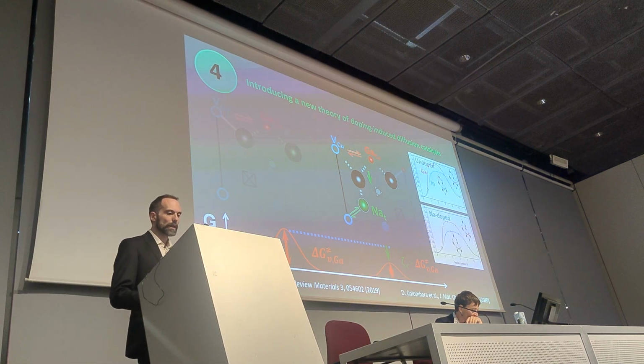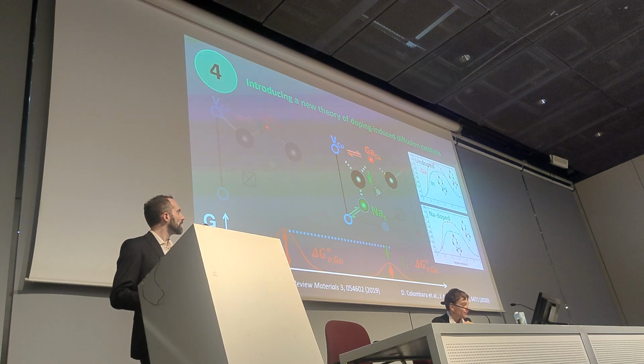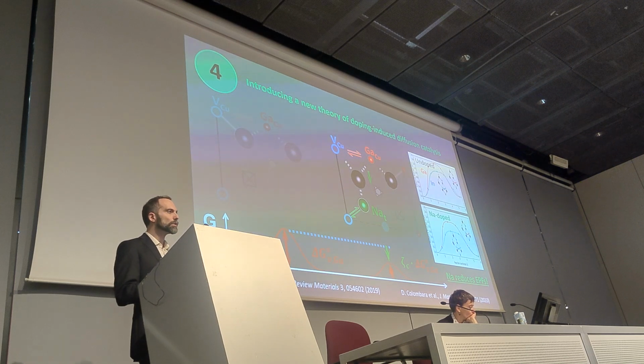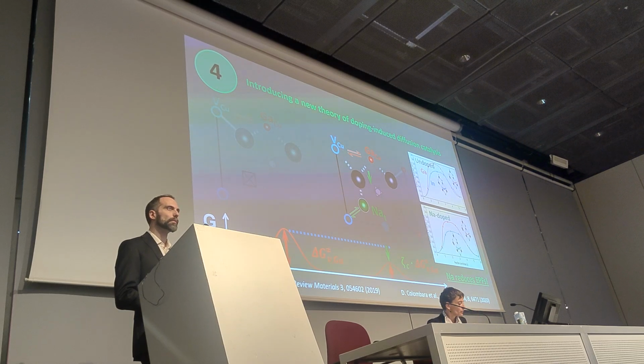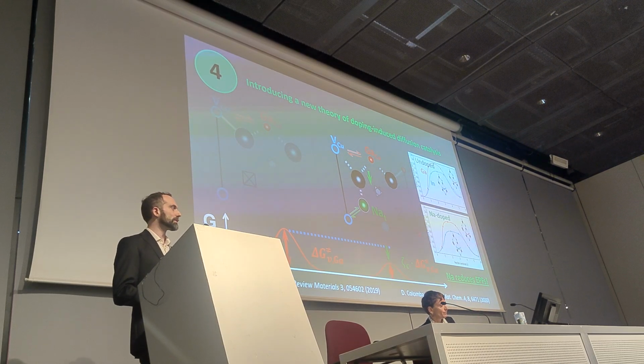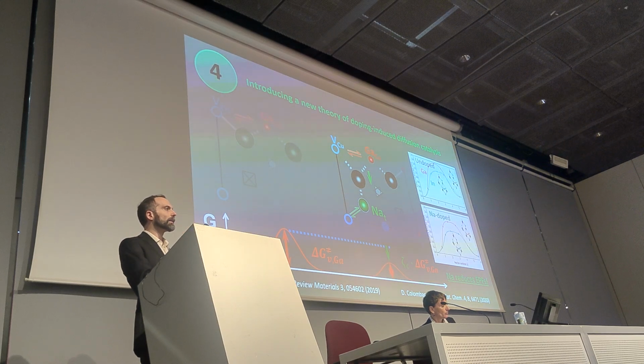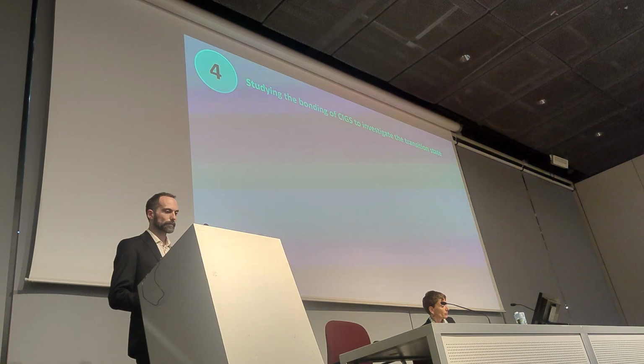So we asked collaborators in Finland to help us test this hypothesis, at least computationally, and the DFT analysis they performed is at least supportive of this hypothesis. So my conclusion from all this is that sodium effectively is good in CIGS. It helps to improve the performance because it reduces the extent of electrostatic potential fluctuations by easing the diffusion of point charge defects within the material.